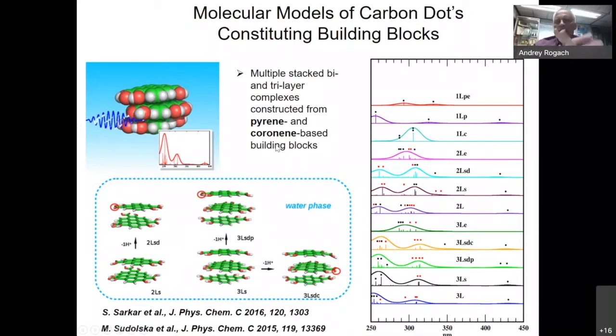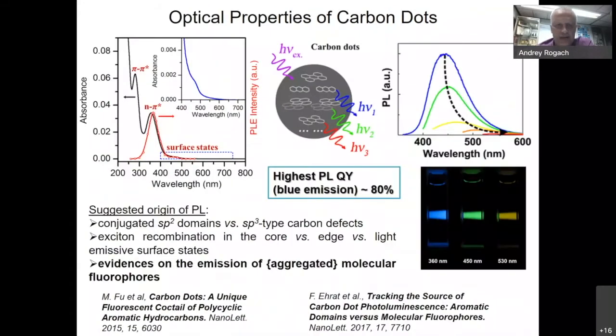Many people look at carbon dots like they are made up from these building blocks. This understanding can be well supported by theoretical calculations, by modeling. And this is what has been done by my colleagues in Czech Republic, at the University of Olomouc. They could reproduce absorption spectra very well when they did modeling for energy structure and optical spectra of carbon dots built up from these pyrene and coronene building blocks. So I go back to my previous slide now. And this build-up has also been confirmed experimentally in this paper, Fu et al., where I'm also a co-author. This work was done by my previous group in Munich.